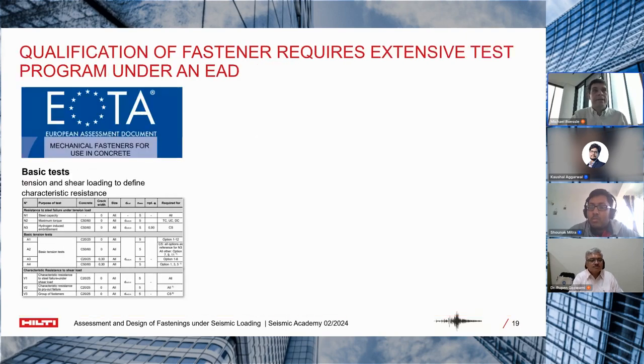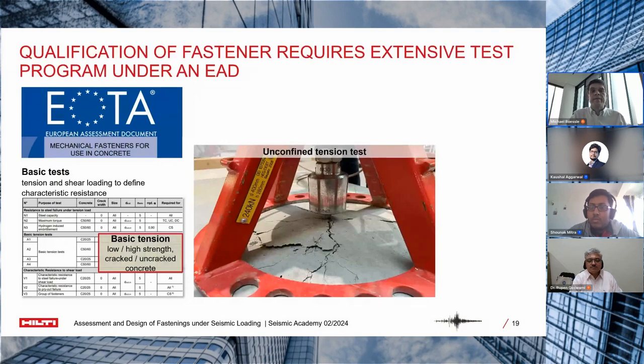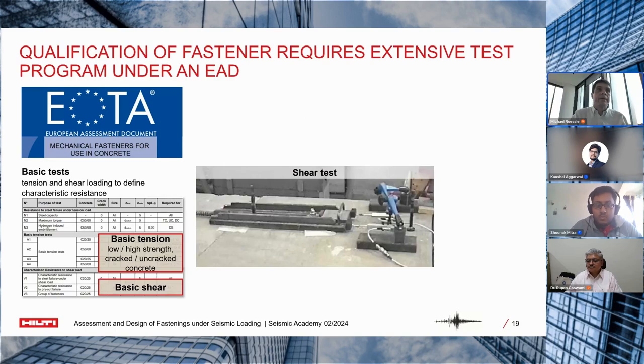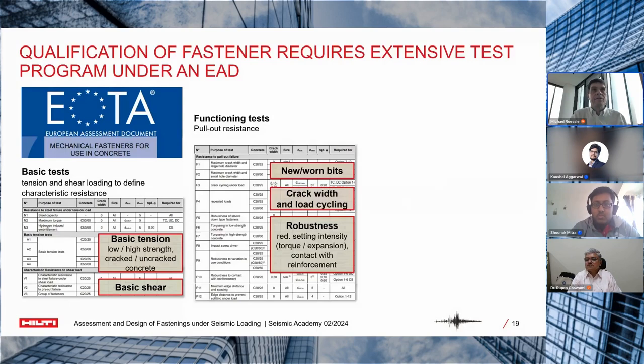So there's a test protocol for the basic tests. That's basically tests that everyone would expect that we are doing with anchors. It's those sort of pull-out tests in high strength and low strength concrete, also in cracked and uncracked concrete. And then for sure, we are doing basic shear tests. This is just monotonic shear testing where we check the capacity for those anchors under shear loading. We test our products to make them robust with new and worn drill bits.